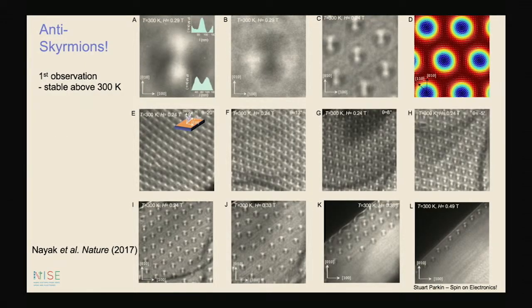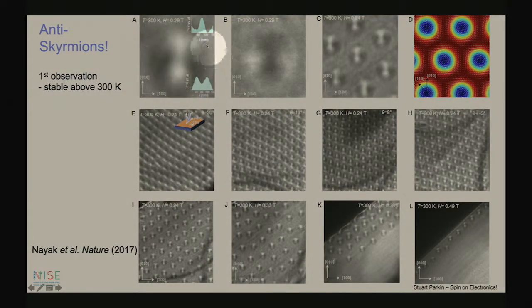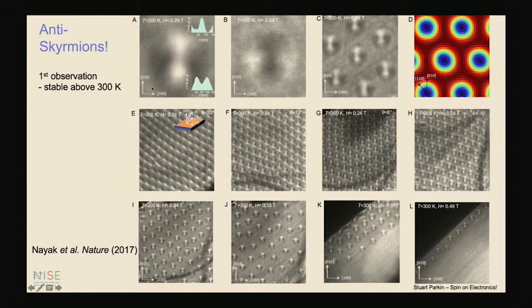Well, where we first saw these anti-skyrmions, we published this in Nature about 18 months ago. You can see on the top left, can you see this picture? This is the Lorentz micrograph, and I think you can see that it looks pretty much like the calculated pattern. You see two white lobes and two black lobes, cloverleaf. So it's a beautiful, direct determination that we have anti-skyrmions.